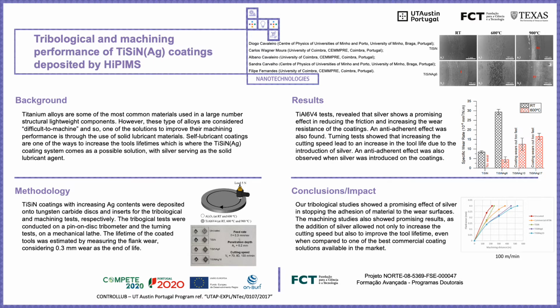All the tribological tests were performed on a standard pin-on-disc equipment, and all the turning tests were performed on a mechanical lathe. As seen on the e-poster and on the figures on the methodology part, we can see the different parameters we used on the tests, either for the tribological and for the machining tests. Just as a reference, the end of life for a tool was considered when the flank wear in the tool reached 0.3 mm.